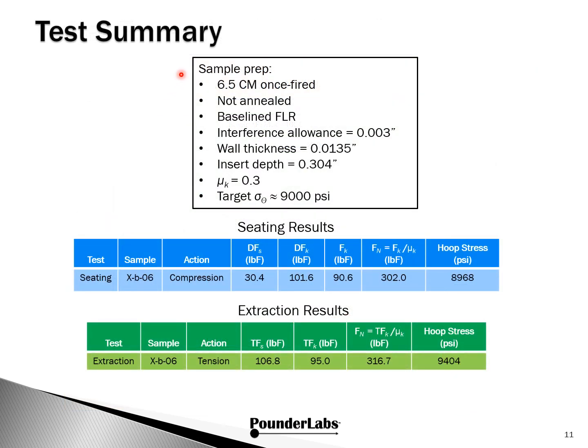And here's the summary of our testing on the Instron. To review, sample prep, we're using the 6.5 Creedmoor once fired case. It's not annealed. We're using our baselining techniques for full-length resizing. The interference allowance is set for 3 mils. Wall thickness is 13.5 mils, and the insert depth is 304 mils. We're still leaving the kinetic coefficient of friction at 0.3, and from previous analysis, we know that hoop stress for this sort of a sample should be around 9,000 psi.